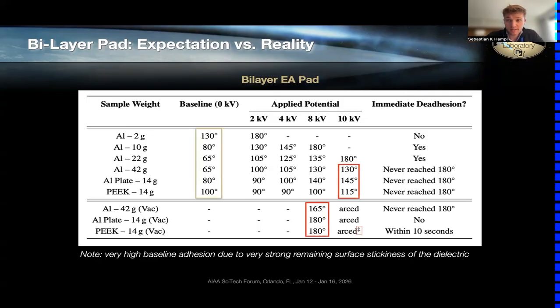What was consistent, though, and what is important to note, is that we retested an aluminum plate, an aluminum sample, and a dielectric sample, in this case polyether ether ketone, both in atmospheric conditions and vacuum. And in vacuum, all of these 3 samples performed significantly better, and we saw a higher electroadhesive force. And on top of that, we also again saw more remaining residual polarization because we did not have immediate deadhesion.